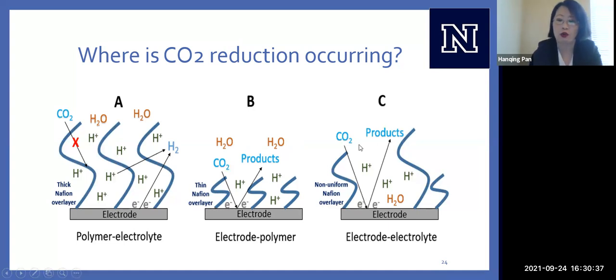Our third scenario is, what if we have a non-uniform Nafion overlayer? What if I didn't drop cast correctly and the Nafion has holes? If the Nafion has holes, our electrode is being directly exposed to our electrolyte. And so CO2 is coming in, bypassing the Nafion. So it's just going through these holes, getting reduced on the electrode surface, generating products. We're also seeing hydrogen. And now the reaction is happening kind of in the middle here at the electrolyte interface.